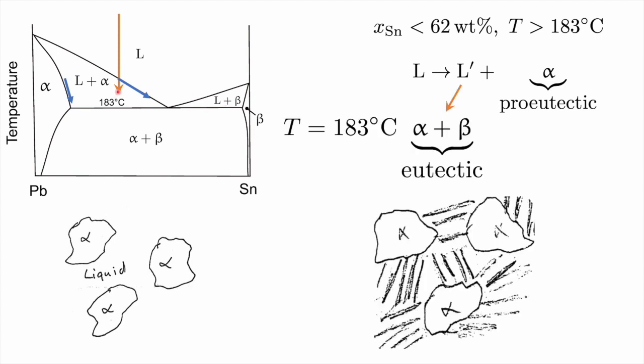Now, once this reaches the eutectic temperature, 183 degrees centigrade, the remaining liquid will also have reached the eutectic composition, and therefore it decomposes into a mixture of alpha and beta, which is the eutectic phase illustrated here. So the microstructure looks quite different: we have a pro-eutectic phase alpha and then a mixture of alpha and beta which forms the eutectic microstructure.